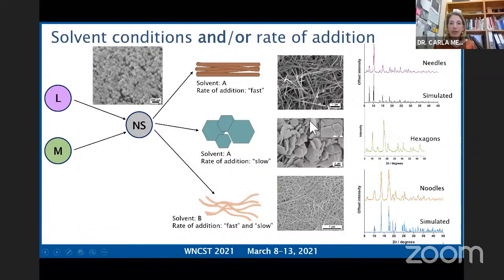The hexagons then, we have, again, a powder X-ray diffraction pattern. We're working on obtaining the electron diffraction data. Again, it's probably a little bit hard to see on the screen there, but these hexagons tend to form stacks. And because of those stacks, we're getting multiple diffraction. And so it's been a little bit problematic getting an electron diffraction data set that's suitable to solve the crystal structure. So that's still in progress. But from the powder X-ray diffraction pattern, we're starting to be a little bit more confident that it's, again, perhaps a new MOF, but that remains to be seen. And then with the noodles, this is a very well-known structure that can and has been produced on the macroscopic scale.